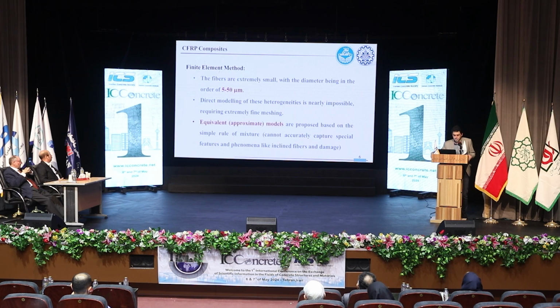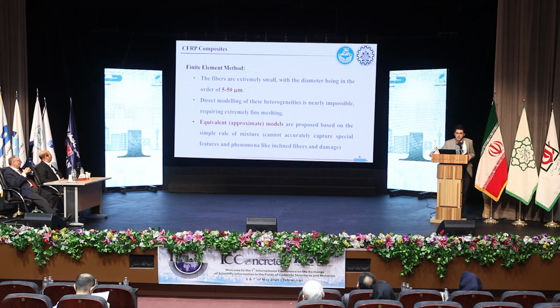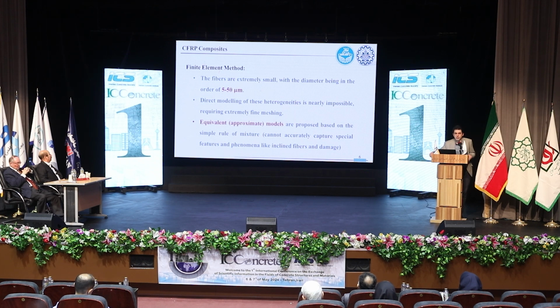So equivalent models are proposed where a simple rule of mixture is used to volume average the properties of these materials to derive a unique material with equivalent properties. In this case, we use these equivalent properties in the finite element method. We reduce the computational cost, but we lose accuracy, and we will show in the numerical results that even with this method, we can't capture the effect of damage, crack propagation, or other failure mechanisms because we cannot capture the real behavior of these materials.